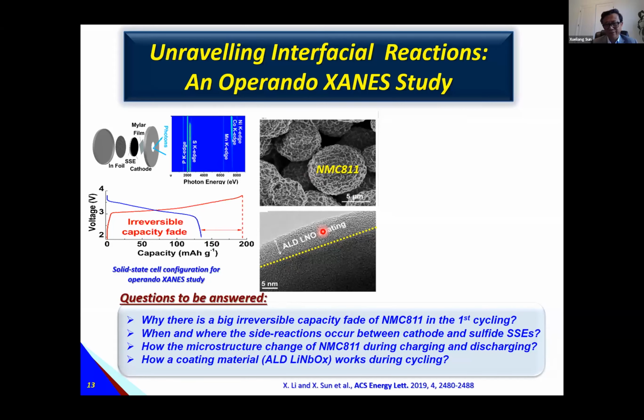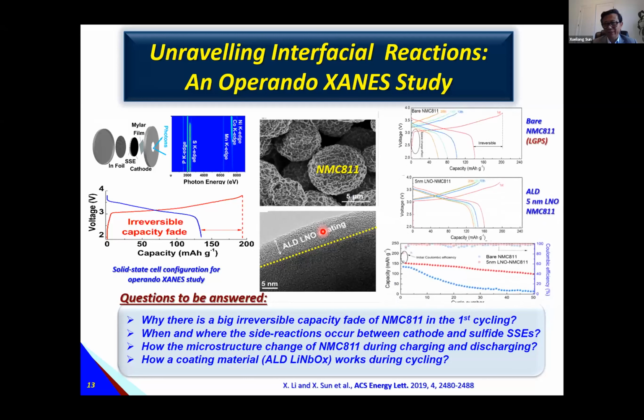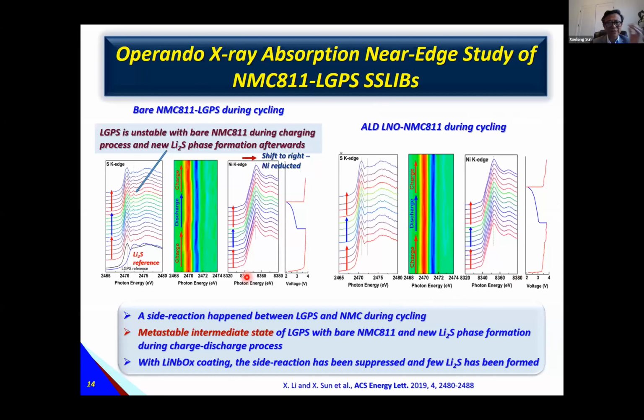In order to answer these questions, we assembled batteries. Without coating, the battery runs very badly. With an ALD coating using lithium niobium oxide, the battery can run smoothly. So we try to understand what happened at the interface. Using experimental techniques, we found new features during cycling corresponding to lithium sulfide.